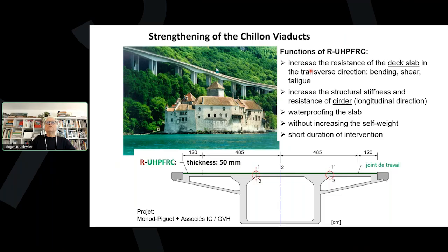And to fulfill several functions, increase the resistance of the deck slab in the transverse direction, and then also in the longitudinal direction, this thin layer of UHPFRC increases the structural stiffness and resistance of the girder, the haunch, the box girder, by about 20%. And then, of course, it's the waterproofing layer.